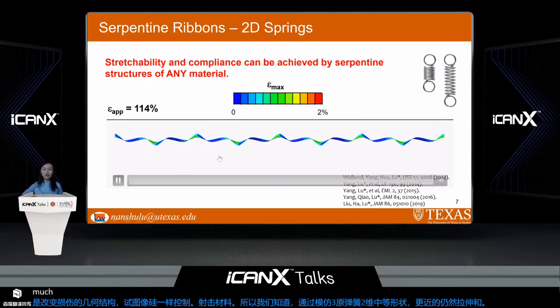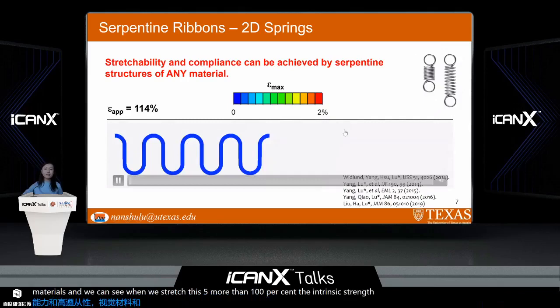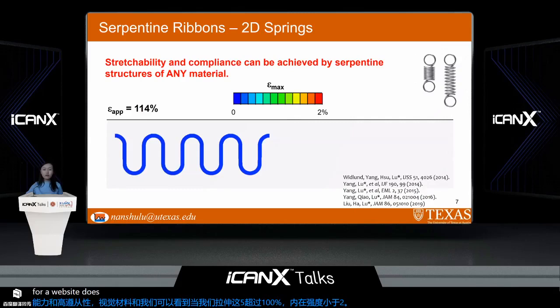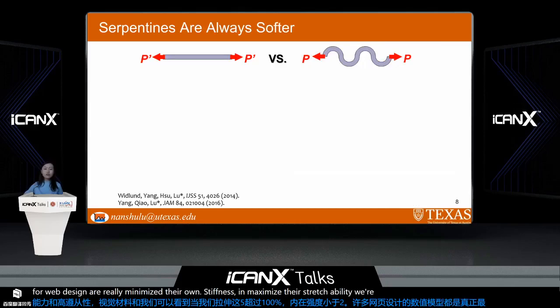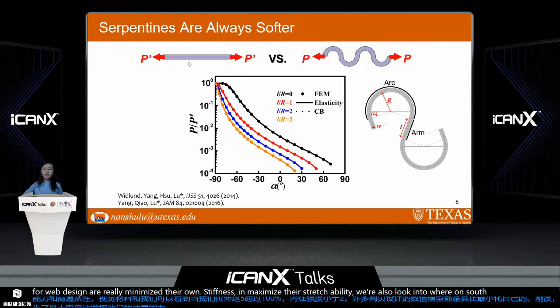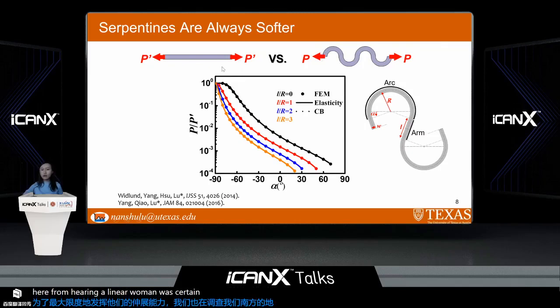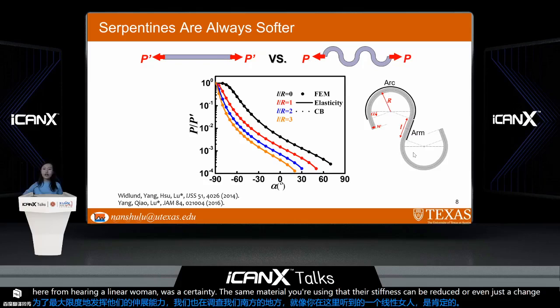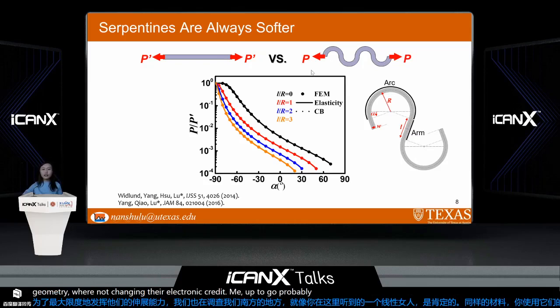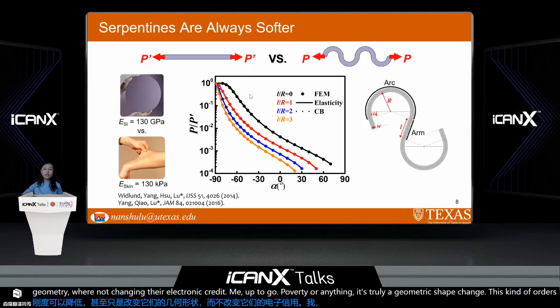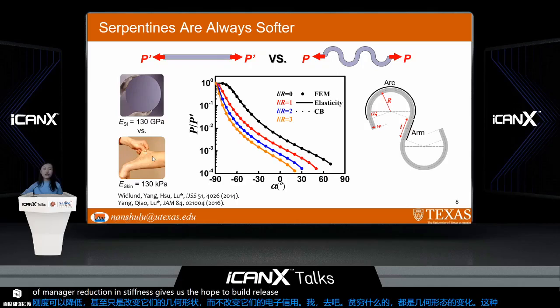And we can see when we stretch this by more than 100%, the intrinsic strain inside is less than 2%. We have done a lot of theoretical and numerical modeling for this serpentine design to really minimize their stiffness and maximize their stretchability. We also looked into their softness, as you can see here, comparing a linear ribbon with a serpentine ribbon of the same material. We can see that their stiffness can be reduced by orders of magnitude, even if we just change their geometry. We're not changing their electronic property, optical property, or anything. It's purely a geometric shape change. And this kind of orders of magnitude reduction in stiffness gives us the hope to build really skin-soft, tissue-like electronics out of intrinsically stiff materials.